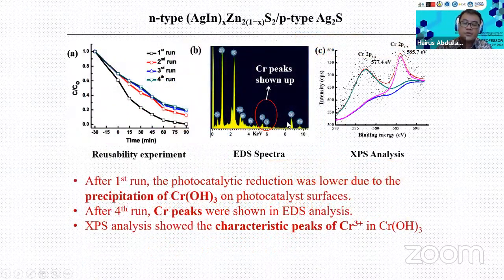Then here also shows the proof that after the photocatalytic reaction, we have a chromium peak in the EDS analysis. The performance is a little bit degraded because the surface of the catalyst is covered by chromium. This is also proof that after the reaction, in the XPS analysis, we also show chromium with a very specific binding energy.